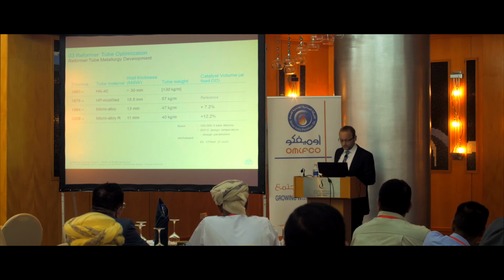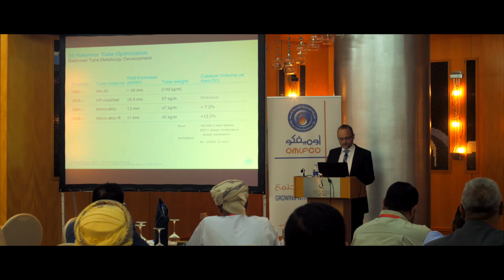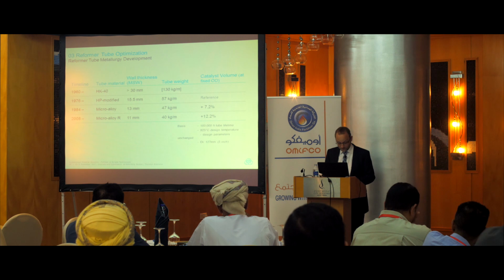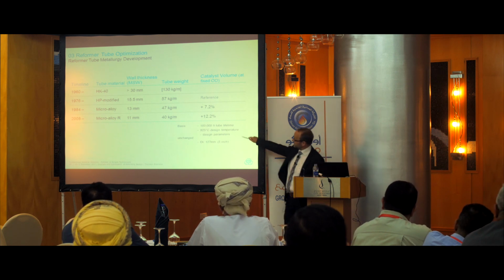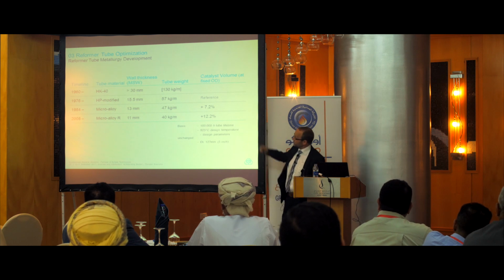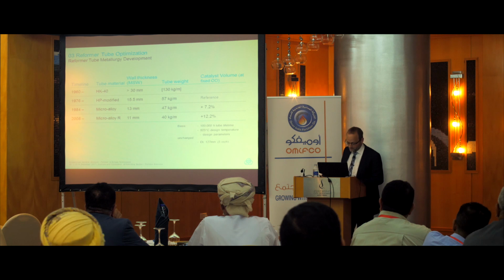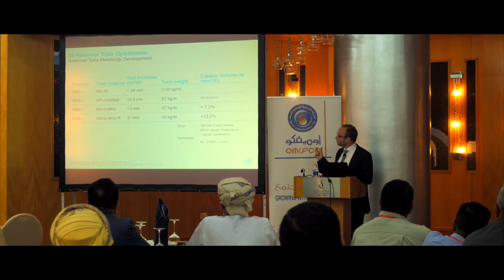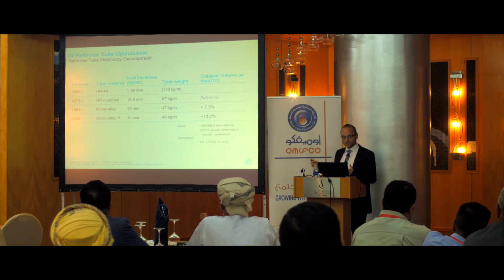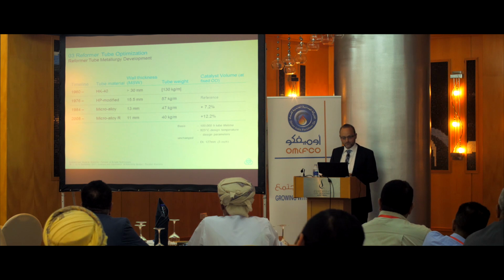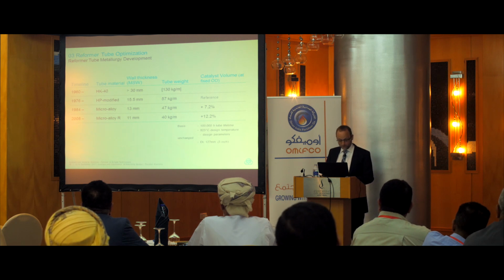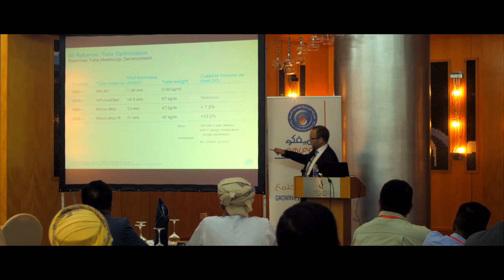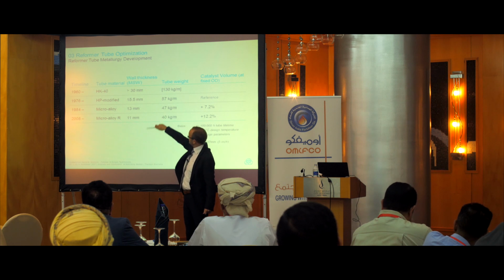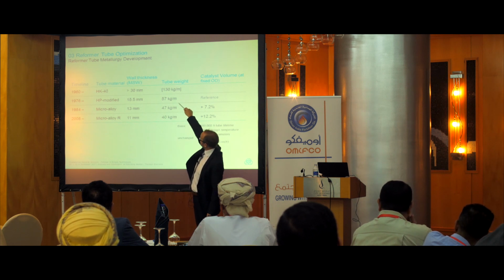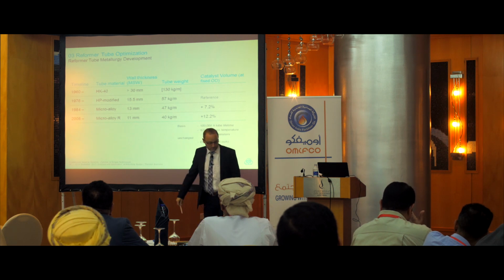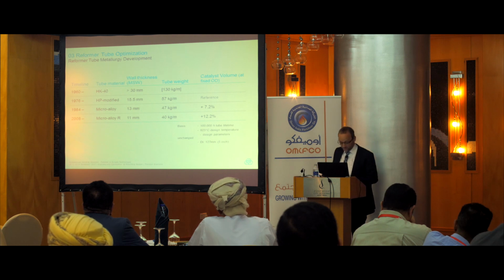So with these data, we computed an example which shows the effect of the higher creep rupture strength. First of all, with the calculated design data which we are using today, an HK40 tube would have more than 30 millimeter wall thickness. But that is just a theoretical value, because a 30 millimeter wall thickness you cannot cast, and the thermal stresses within the wall would be too high, and that would limit the tube life dramatically. Interesting is the thickness reduction from HP to microalloy R, from around 15 to 16 down to 11. And with this, of course, the decrease of tube weight. And this would result, of course, in a huge cost saving.